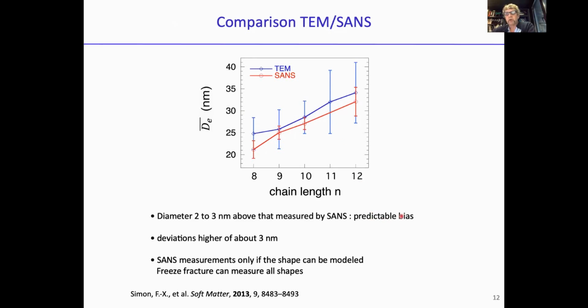And it was a predictable bias because, like I said, we sputtered the particles with nanoparticles. And the deviation is also higher, by about 3 nanometers, which is also due to the technique, which includes the sputtering of the nanoparticles. So the freeze fracture reproduces very well what we saw in small angle neutron or X-ray scattering. Just keep in mind that the SANS measurements can be modeled only if you know the shapes already.